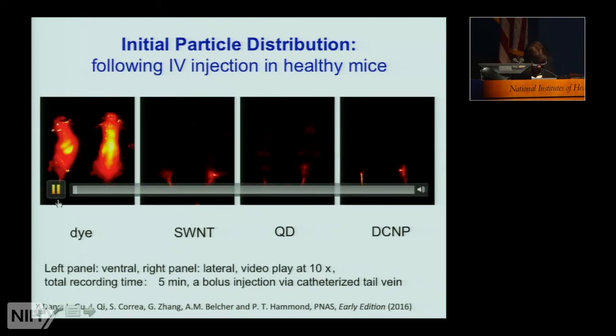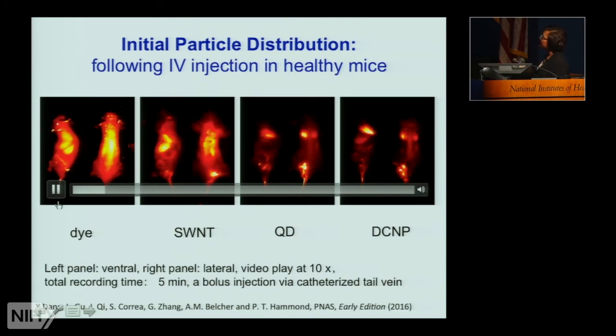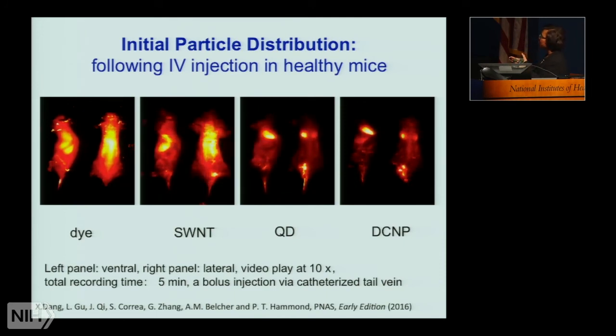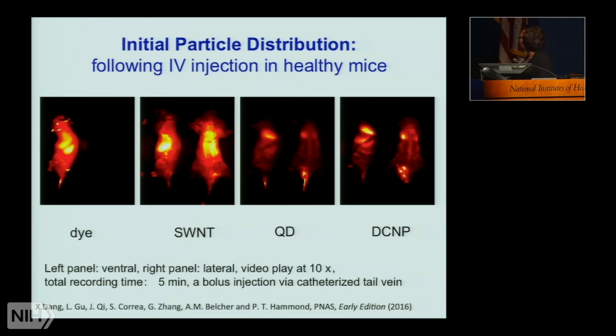And what we found is that by using Angie's system, in comparison with the others, we can completely escape a range of autofluorescence that we experience with dye molecules and single-wall nanotubes, and actually see what's going on inside of these animals without that autofluorescence using the down conversion nanoparticle and quantum dot. In fact, with the down conversion nanoparticle, we can see fine structure of blood vessels, musculoskeletal structure, and even the beating of the heart is much more visible.